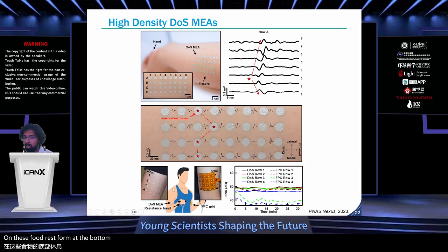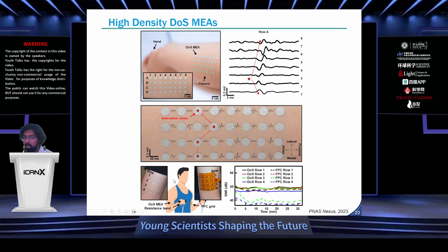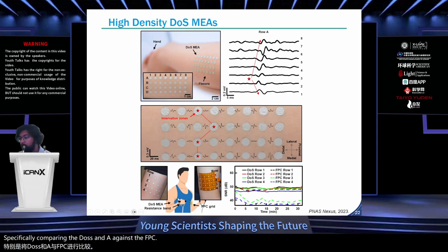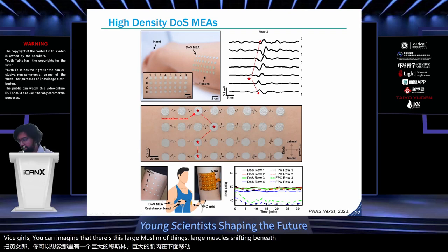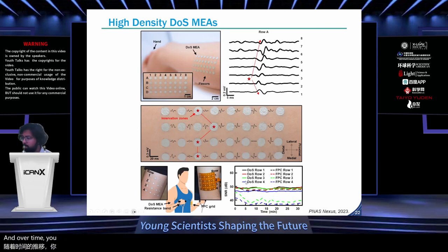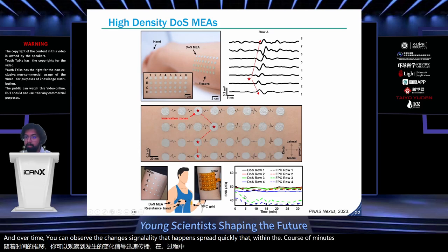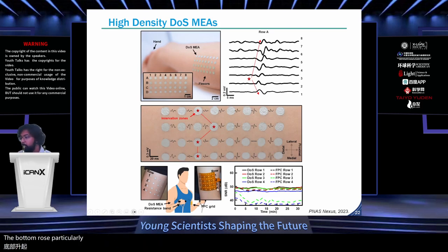At the bottom here, we show a comparison of the signal quality during large muscle movement, specifically comparing the DOS-MEA against the FPC grid during resistance band bicep curls. You can imagine that there's this large muscle movement, large muscle shifting beneath the MEA. And over time, you can observe the change in signal quality, and it happens rather quickly that within the course of minutes, the bottom rows particularly, which experience a lot of deformation due to muscle movement beneath, begin to lose contact with the skin and eventually